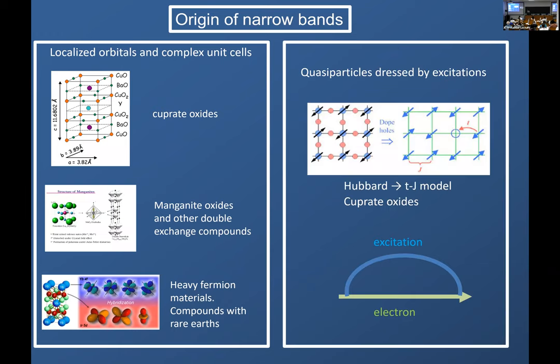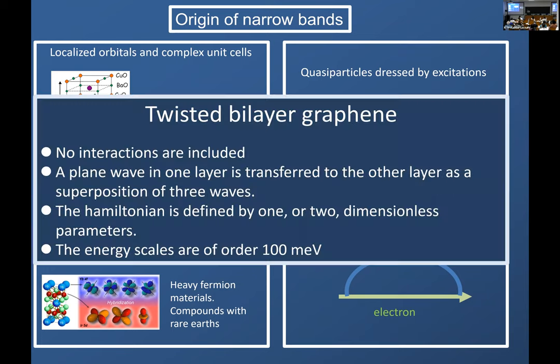Things become more complicated as studied by Leon Balents and others when you go beyond the first magic angle, but I will concentrate on the first magic angle in the following. As I said, in other systems the flat bands, because they are based on highly localized orbitals which are far away from each other, become flatter because of interactions. They are renormalized because the electrons need to drag excitations of the medium and the effective mass increases and the bands become flatter. None of these things is included in the continuum model I just outlined for you.